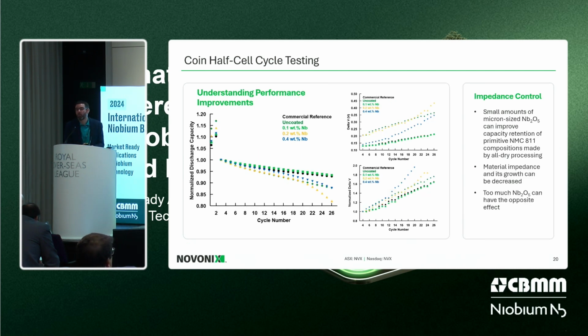To understand a little bit about why too much niobium isn't necessarily the best thing when you're dealing with surface coatings, we again return to our metric of delta V, which is our analog for impedance within the cell. So the left-hand slide is no different. It's the same data as the previous slide, only it's there for reference. And then in the middle, I'm showing again the absolute value of delta V on top, and then a normalized version to look at impedance growth within the cell as you cycle under these conditions.